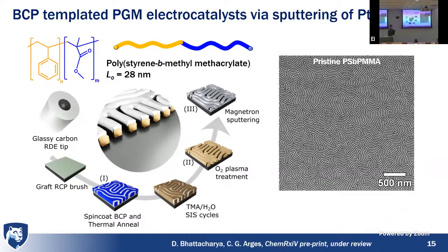We wanted to measure the electrochemical reactivity, so we had to learn how to do this process on glassy carbon tips. This is the substrate that we use in that experimental setup. We grafted a non-preferential layer that makes sure both block copolymers will sit perpendicular to the surface. We'll put this block copolymer on top. We'll spin coat it. We anneal it. We've used a very simple one, polystyrene-block-polymethyl methacrylate.